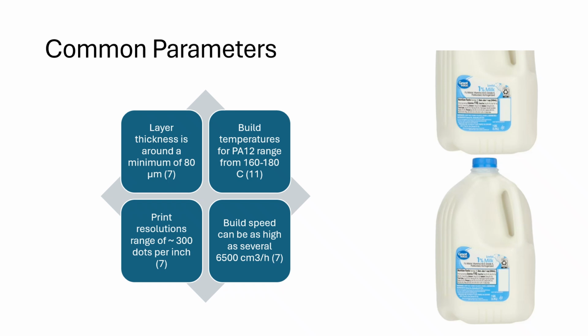Typical layers are about 80 microns thick. Build temperatures for PA12 are usually between 160 to 180 degrees C. Print resolution is roughly 300 dots per inch, and build speeds can reach up to 6,500 centimeters cubed per hour, or approximately 1.7 gallons per hour, depending on geometry and machine size.